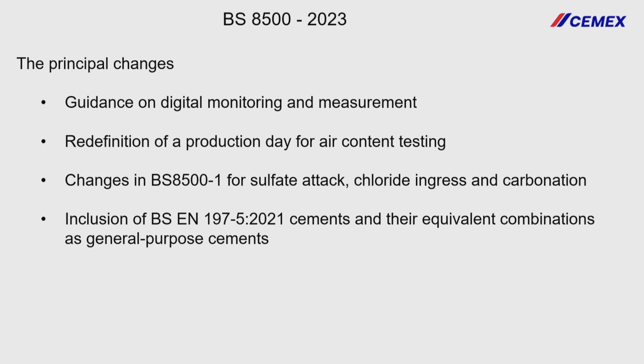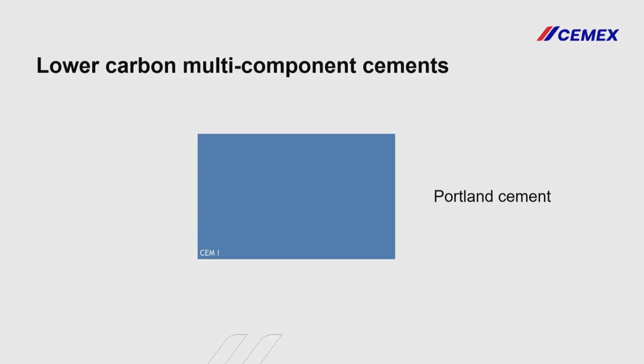And in both Part 1 and Part 2, and this is the exciting bit, this is where the test comes in about cement designations. We could then include BS EN 197 Part 5 cements. So in blunt terms, that's CEM II/A-L, Portland limestone cements, plus fly ash, plus GGBS, CEM I plus limestone fines, plus GGBS, plus fly ash. So going back to basics, we think about the opportunity for lower carbon cements.